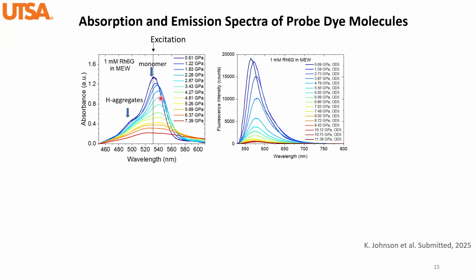So from the absorption spectrum, we have identified two peaks. One is the monomer absorption peak around 535 nanometers, and we also have the H aggregates absorption peak around 500 nanometers. By saying H aggregates, that means the dye molecules are stacked face to face, and perfect H aggregates do not emit light. And also we see an overall peak shift to the red. This redshift of the absorption actually indicates the reduced energy gap between HOMO and LUMO energy levels. And also the relative intensity is reduced for H aggregates over monomer, and that indicates an increased ratio of H aggregates over monomer in the solution.